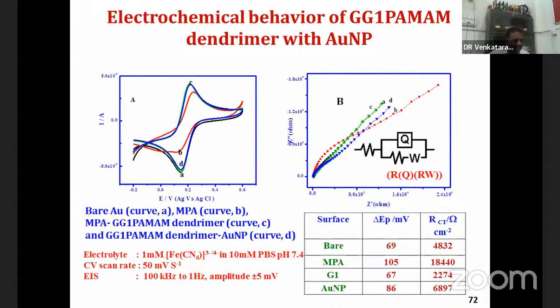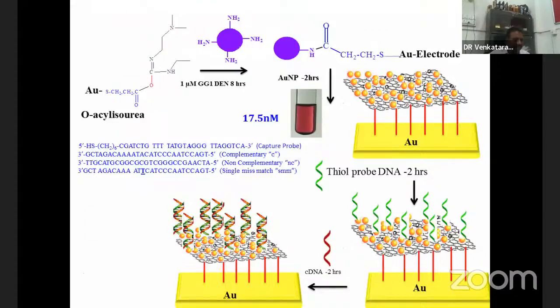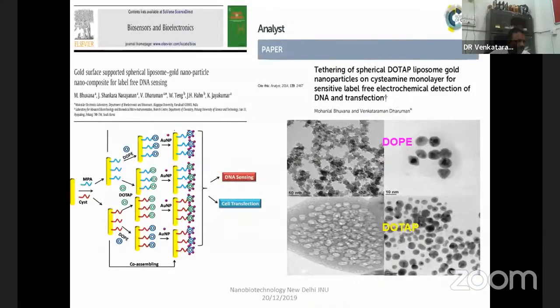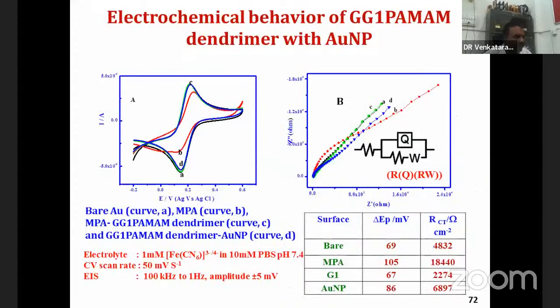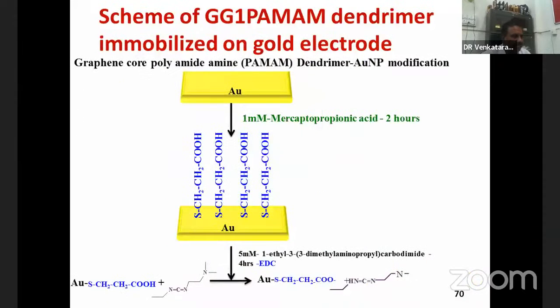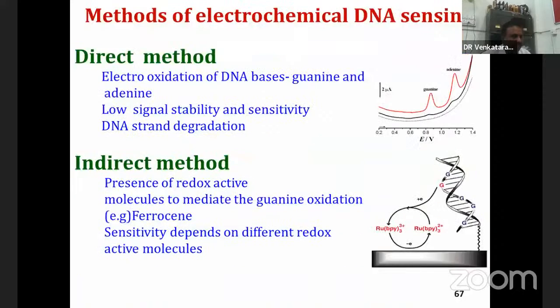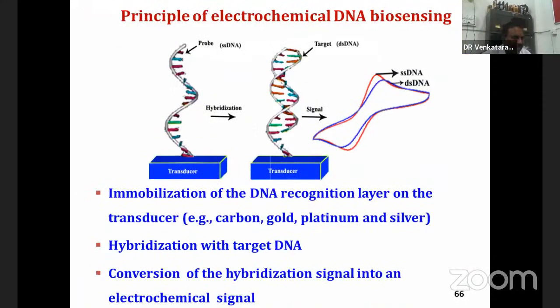And once we attach it, what we did was we put the strands and helical formation. I lost that PowerPoint in preparation, where what we get was the signal like what I showed earlier. No, this is the signal difference. The same kind of signal difference we get when you use the graphene and gold composite between the single strand and the double strand.